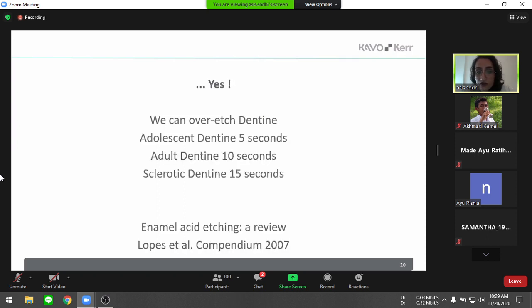So I could refer to this study that outlines adolescent dentine, which is younger dentine, softer dentine, should be etched for about 5 seconds. If it is an adult dentine, you want to do 10 seconds. And sclerotic dentine, which is aged dentine, which is older dentine, you can etch for about 15 seconds. And these are the guidelines based on the enamel acid etch review that was published in 2007.